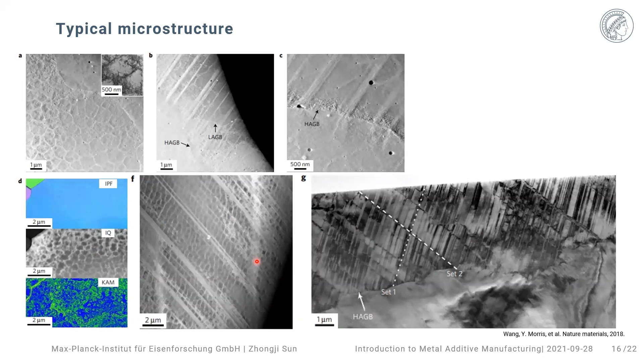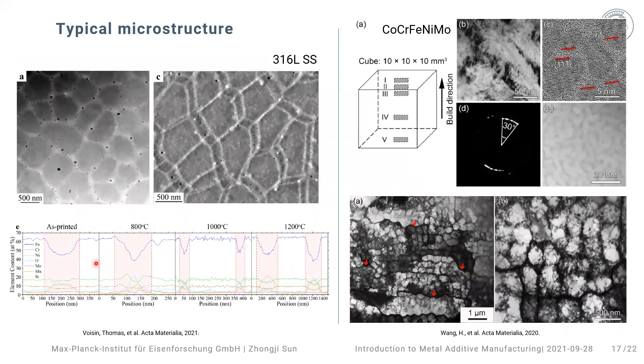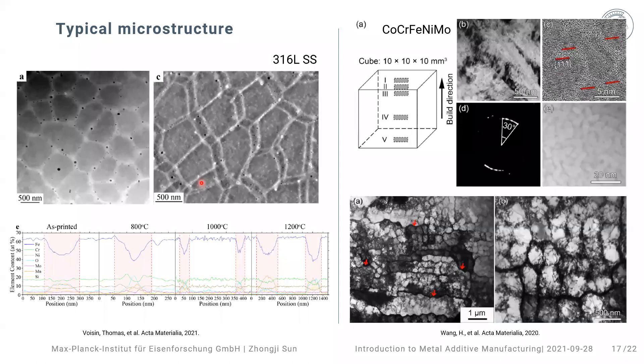If you continue to pull the sample from 3% to about 10% and 20%, the cellular structures give away their structure once dislocations come in. The paper concludes that it is this unique cellular dislocation structure which contributes to the concurrent increment of strength and ductility. Since this is a unique feature pertaining only to AM, people began to investigate why these cellular structures form in the first place. Under very high resolution TEM, nano-oxide precipitations were found only within the dislocation cells.